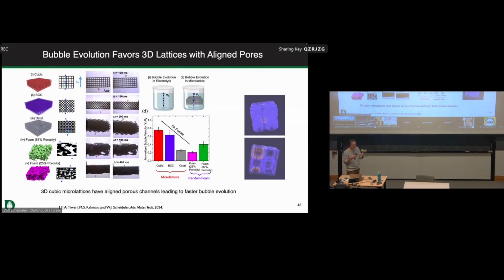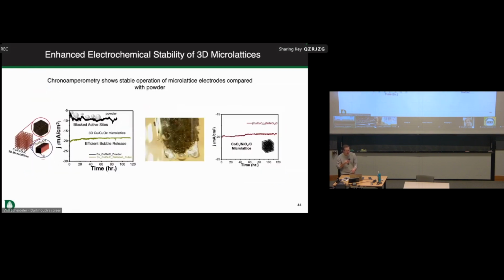So for one thing, the bubble speed depends on essentially the size of the bubble. But for another thing, it depends on whether the buoyant force is aligned with the channels that we have. Now, the cubic lattice is nice because the buoyant force is now perfectly aligned with the channel throughout the whole slab of the material. So we think this is like an interesting property that you couldn't get from a random material. It simply won't ever be the case that it will be aligned with the pore structure.